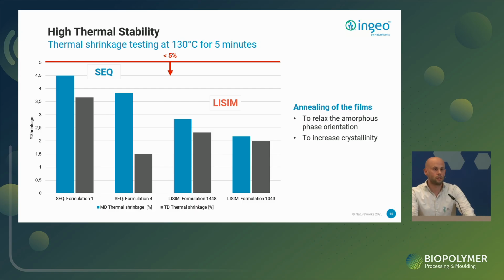Also very important for such films is the heat stability, and we just heard that PLA has limitations in that. What you see on the slide is various formulations that we have developed. The left-hand side is a sequentially stretched material, and on the right-hand side in red is the simultaneously stretched material. And due to the processing technology that we have applied, for example, by annealing the film in the extrusion or